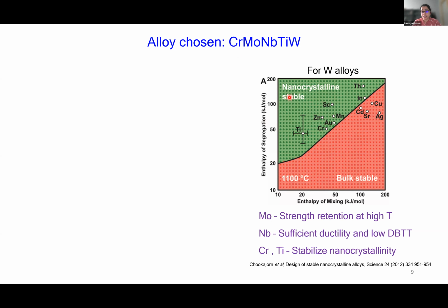The region here in green contains elements like chromium and titanium, majorly, which are close to the boundary. What happens is that when we add elements from this stable region, they tend to segregate at the grain boundary, making the grain boundary stable. It pins the grain boundary so that it cannot grow even at such high temperatures. So from this, we have chosen chromium and titanium. We just want to see, when we extend from the binary to a multi-component system, whether this idea will be applicable or not. That was the reason why we chose chromium and titanium, just to stabilize the nanocrystallinity of the alloy.